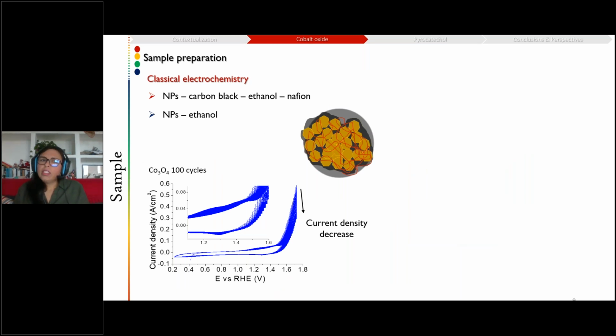One was the sample preparation. A classical ink for electrocatalyst testing would contain the particles, in our case cobalt oxide, but most of the electrocatalytic materials, especially nanoparticles, will be tested in this way as well, with a carbon active material that will allow the percolation of the electrons. In our case it was carbon black. Nafion that will be used as a polymeric material to keep everything in place, and in this case ethanol to disperse everything. This will allow the particles to stay on the surface of the electrode and not go away upon rotation when we are doing our experiments.